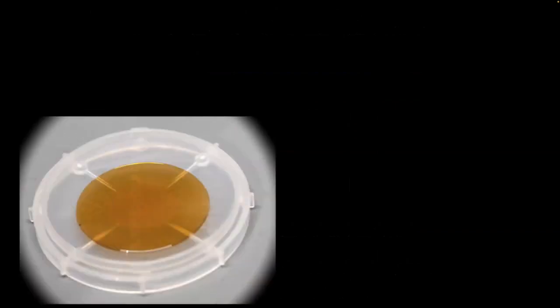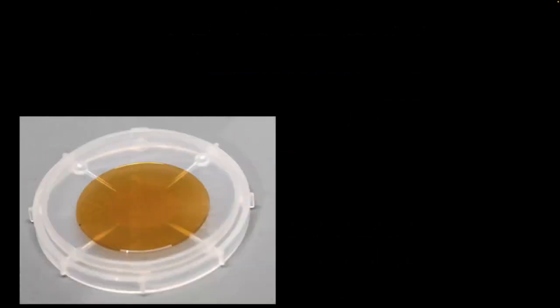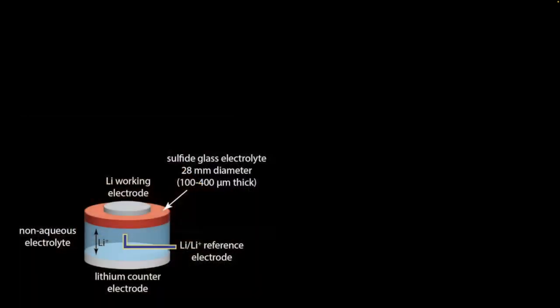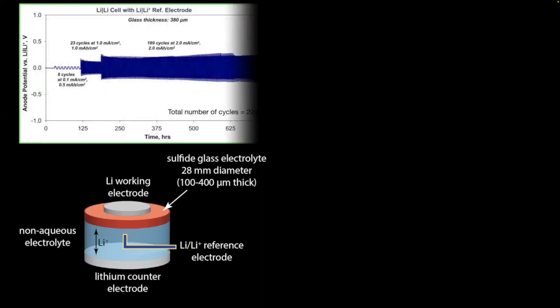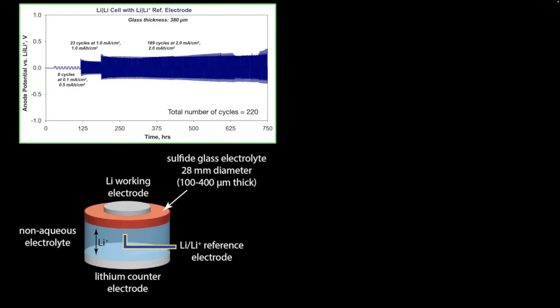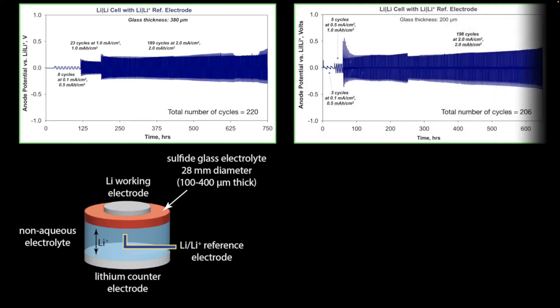Okay. So with regards to simple testing in cells, we take these glass discs. We bond lithium metal to the glass disc, and then we can put it into a test cell, cycle it against a lithium counter or NMC cathodes. And you can see here that we don't see any evidence of dendritic shorting. They cycle quite well. That's 400 microns, 200 microns glass.